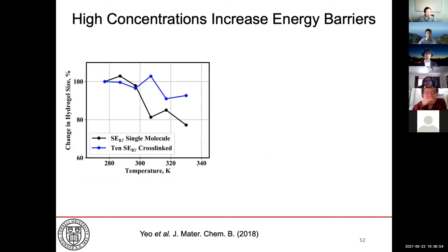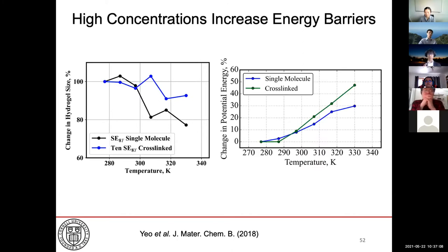And again, if we were to perform the same temperature sweep, we can see a very similar trend in terms of the experimental data, of the significant suppression of the deswelling at high concentrations. Now, by analyzing the change in potential energy, the suppression of the transition can be explained by the individual cross-linked molecules encountering much higher energetic barriers, such that above the transition temperature, the energy curves actually diverged, such that each molecule in the cross-linked model had much higher average potential energy than that of a single molecule.